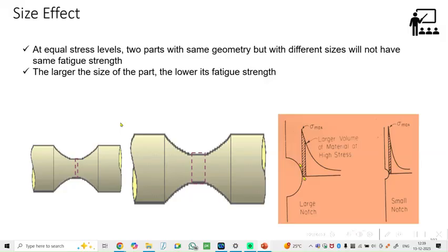The effect can be explained mainly by the volume of material under stress. The larger this volume, the greater the possibility of encountering metallurgical defects like porosity, interstitial elements and so on. In general, fatigue damage first appears on the surface of parts. Obviously, that's known. The crack starts from the surface. Taking two aspects into account to improve fatigue strength, first the surface macrogeometric aspect: poor machining gives a surface roughness that increases the local stress level. Crack initiation is therefore delayed when roughness is low.